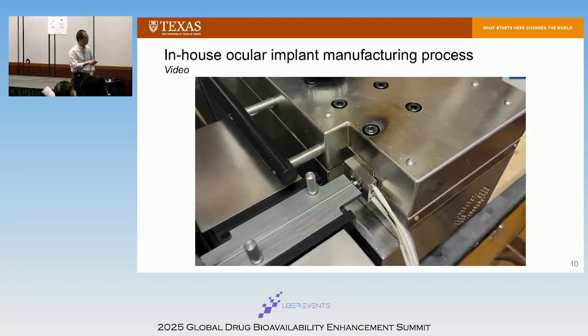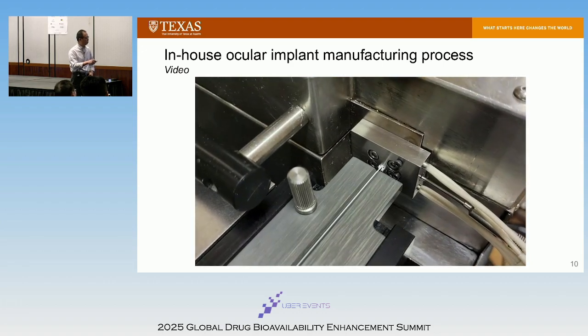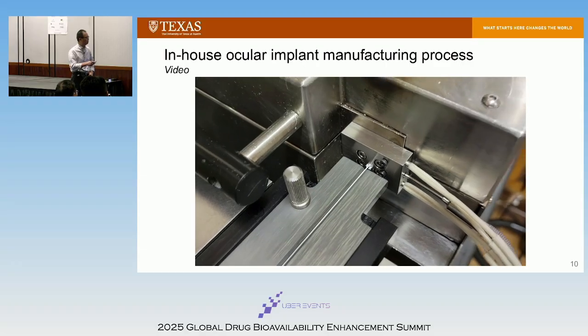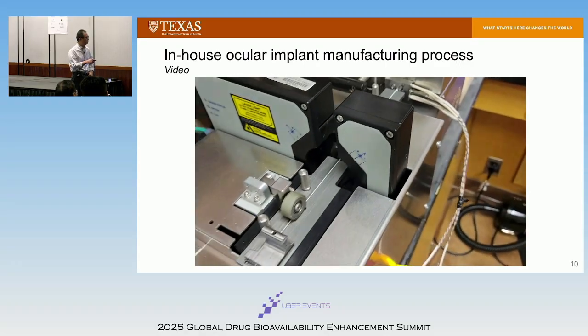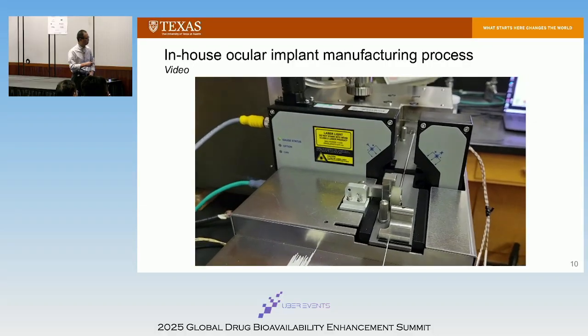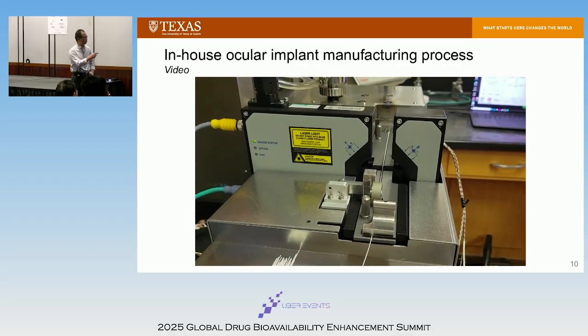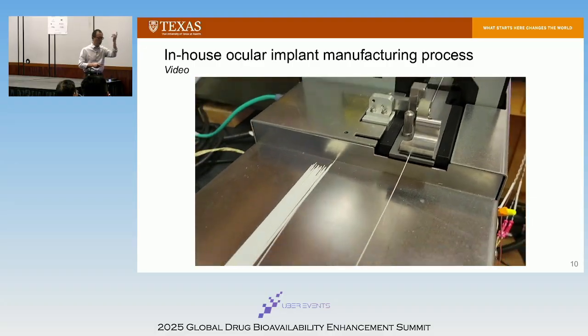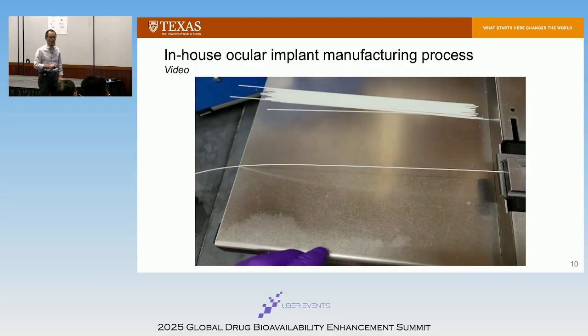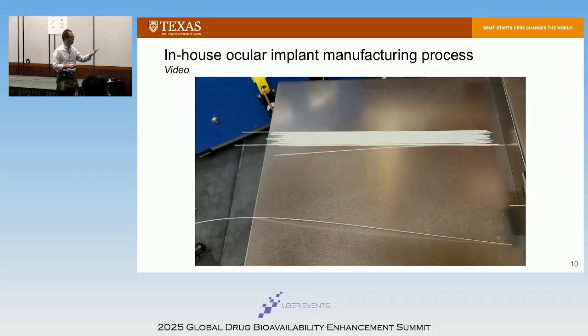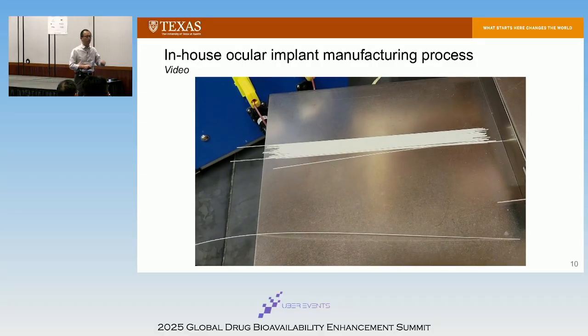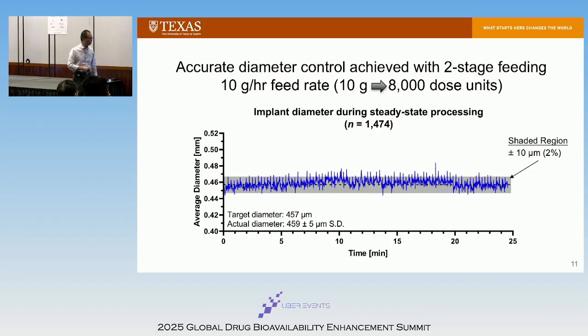And then second step extrusion, we're processing at about 110 degrees C. The stuff comes out. This is the guide plates, goes through the laser gauge. And this is the puller. We worked with a company in California, made this custom-made puller. It's a special puller. And we have this very consistent diameter. So in a commercial process, you may want some feedback loop, right? But here, we can't afford it. But we can control this very precisely, okay?